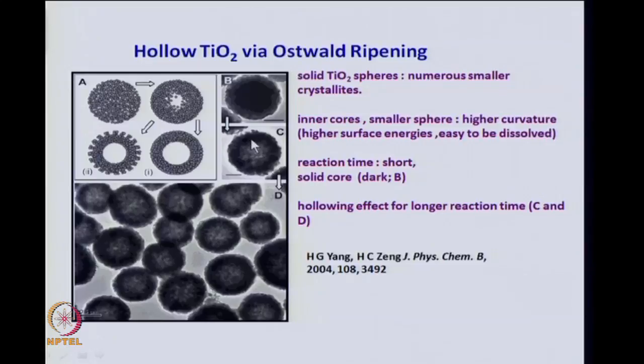So, this is an example of hollow titanium dioxide which is forming through the Ostwald ripening process. So, you see solid TiO2 spheres. Initially, there are numerous small crystallites which you can see here in this model. As time goes on, the inner cores, which are smaller spheres, have higher curvature and higher surface energies, and they dissolve and you get larger particles towards the edge. So, the core particles have higher surface energy compared to the particles on the surface, on the exterior of this large group of particles. So, that will grow, and inside, the particles which have more curvature and higher surface energy will be lost.